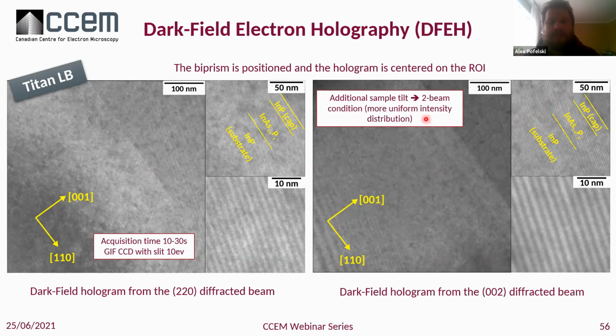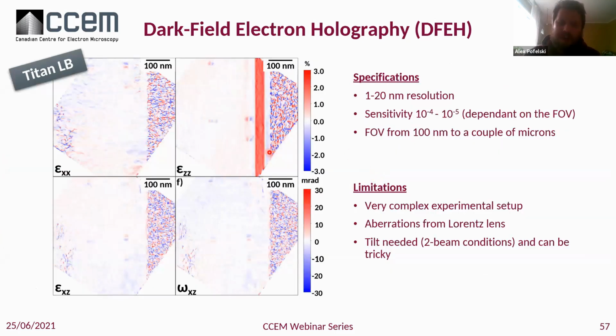And here, for example, on the 002, the diffraction contrast was good with the uniform intensity. On the 220, it was not that great. You see those dark areas, very difficult to find this two-beam condition. So I might be close to an extinction distance here. But at the end, you can get those strain maps.